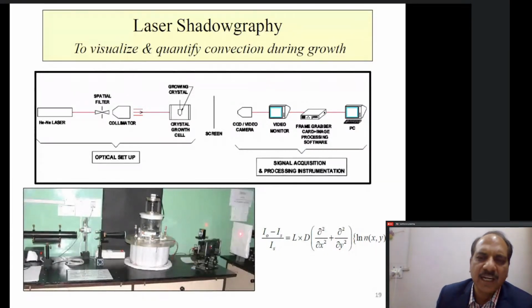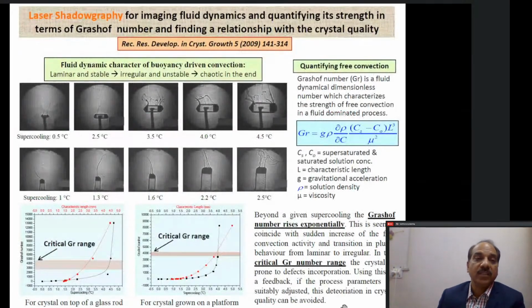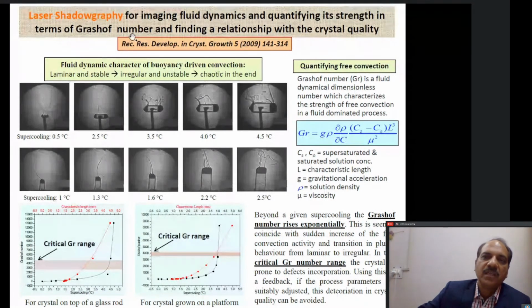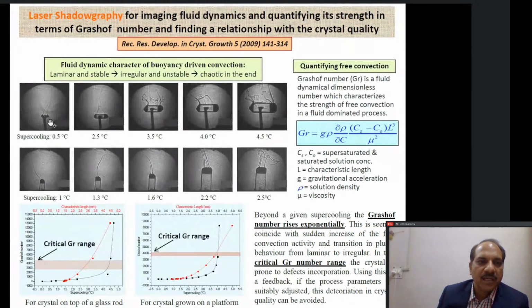This equation is derived with very simple mathematics which can be followed, and this is what we see during experiments. So laser shadowgraphy has been used for imaging fluid dynamics and quantifying its strength in terms of Grashof number and finding a relationship with the crystal quality. So what we do is, this is a seed crystal when the crystal has been put inside the chamber. This is how supercooling is done, because once we are growing with solution growth, we have to cool the temperature. So when you are cooling it, the crystal will start to increase in dimension. And what you see is the increasing dimension of the crystal.